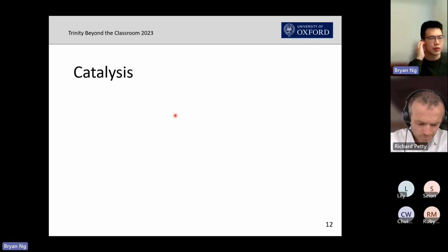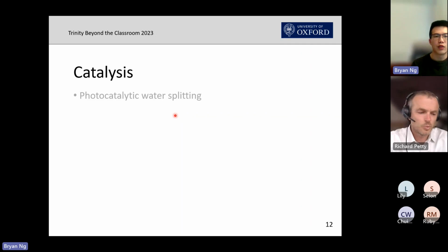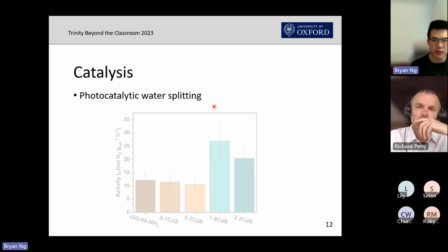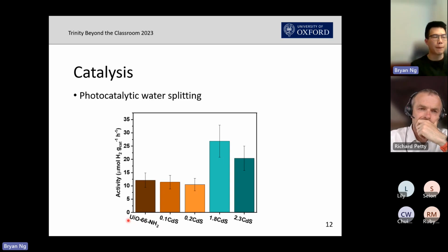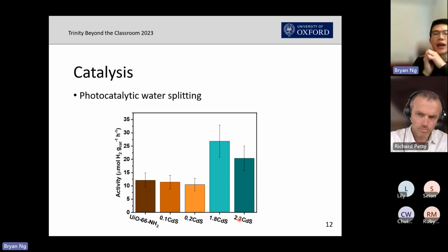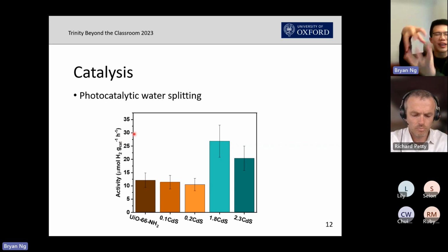These are actual data to tell you what exactly we would be able to measure, and what characterization we need to do in order to be able to tell the story of what is happening. So for example, in this case, I did the photocatalytic water splitting on this. Previously, this is the MOF, the metal organic framework with the amine group on it. And then these four are different loadings or different proportions of cadmium sulfide, which is a semiconductor that I have added onto my MOF. So this is the rate of photocatalytic water splitting. What I have done is I have put everything in the beaker, shone light onto it for one hour, and then checked how much hydrogen is present in my beaker. So of course, it's quite a complicated beaker, not the sort of beaker that you use in the teaching lab of the A-level experimental course.